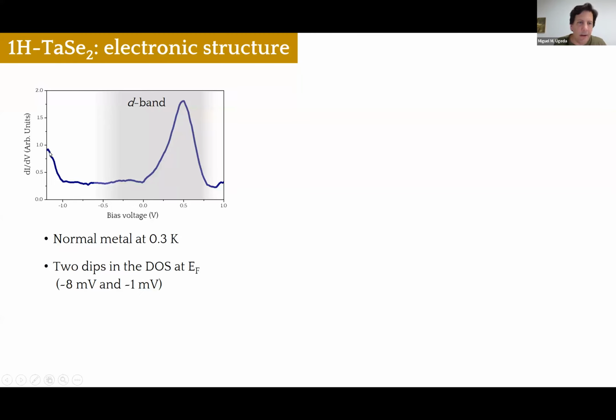So I'm showing you here a dI/dV spectrum taken on single layer tantalum diselenide, where you can see, well, let me clarify that dI/dV is something proportional to the local density of states, right? For those who are not familiar with tunneling spectroscopy, the dI/dV signal is proportional to the local density of states. So I'm showing you here a typical dI/dV curve taken on tantalum diselenide H phase. The shaded region is the part that corresponds to the D band. Okay, in particular, this prominent peak you see here, this shallow peak as well, belongs to this part. This is the Fermi level here. So it's a normal metal at 300 millikelvin.